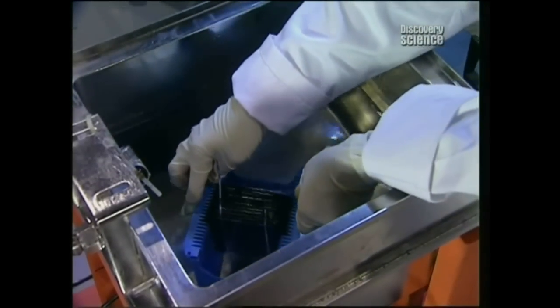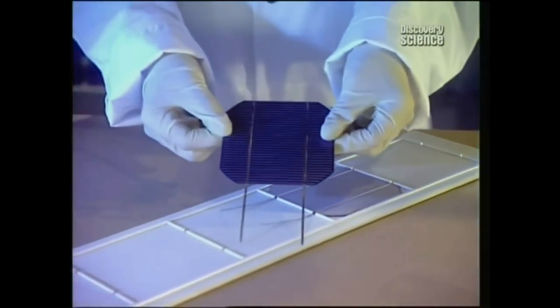Once the soldering is done, the modules are cleaned by ultrasound in water at 60 degrees centigrade. When dried and perfectly clean, they're ready to be modified.